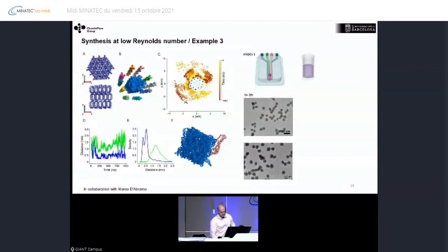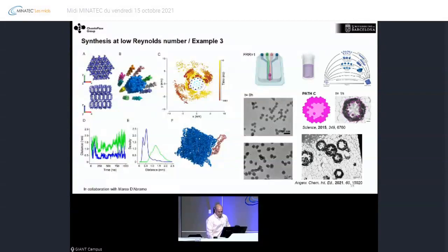Whereas in microfluidics we could observe these small particles, in bulk we could never observe anything at time 0. So if we check the bulk synthesis, we were very surprised to see this mesoscale assembly. As you see here, we have small hexagonal crystallites that assemble to generate the final hexagonal crystal structure. This was very interesting because it was the first example reported in the literature showing this mesoscale assembly for the formation of a spin crossover compound.